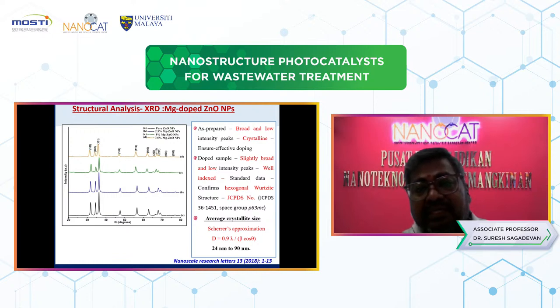As well, you can see the hexagonal structure, which is confirmed from this XRD pattern by using the standard JCPDS card number. The peaks are broad and of low intensity. When you add the doping, you can look at how the peak intensity changes with the doping concentration. And we calculated the crystal size from 24 nanometer to 90 nanometer.